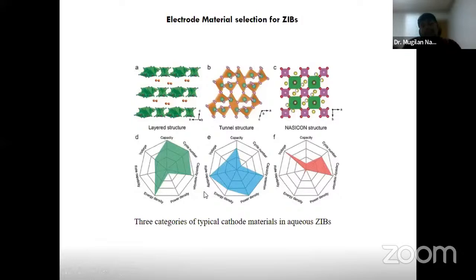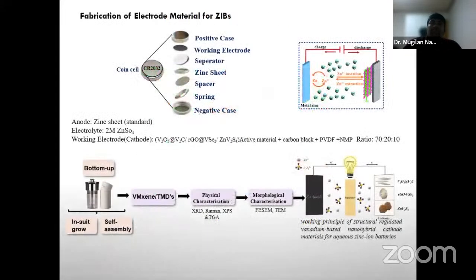So what I basically suggest is that for the layered structure of a metal oxide, transition metal dichalcogenides, or bimetallic transition metal dichalcogenides, we can run a variety of experiments on electrode materials, since a layered structure will give better capacitance. These are the fabrication techniques of the aqueous-based battery: the negative case, spring, spacer, and the zinc sheet, which acts as an anode, and a separator, particularly a polymer-based separator, that we will be using.